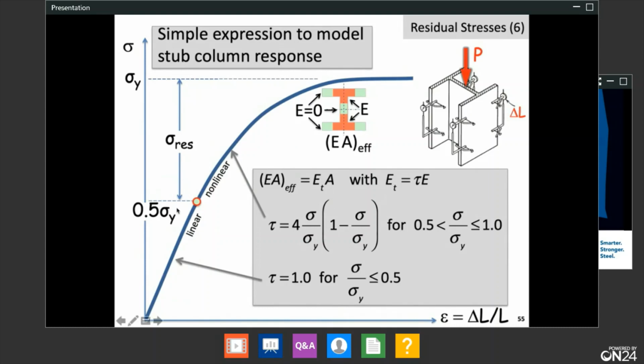Years back, I'm thinking in the 1950s, 1960s, I believe the foundation of this equation came out of the Lehigh research, and they found a very nice model that actually replicated what they were seeing experimentally. And that was, if you started with the yield, subtracted off the residual, and if we were willing to call the residual stress 50% of the yield, that would happen as you were loading the column, now at 50%, and you would go from a nice happy E value to a reduced E value. And the reduction factor is what we call a tau factor.